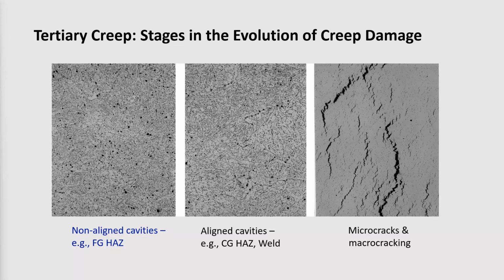And as we're going to talk about shortly, when we look at where the damage can occur, there are different microstructures associated with those different locations. And so the damage can manifest itself in different ways, depending upon where in the welded structure the damage is actually occurring. For example, in so-called type 4 regions, many of you will have heard the term type 4. That generally refers to the region on the outside edge of the visible heat affected zone in a weld, where you tend to have very fine grain size. In those cases, you won't go through that same progression of isolated to oriented cavities to microcracking and macrocracking. Instead, you'll get individual random cavities within the structure. There'll be a higher and higher density of those cavities as damage progresses, and ultimately the material will simply tear apart. So be aware of that distinction.